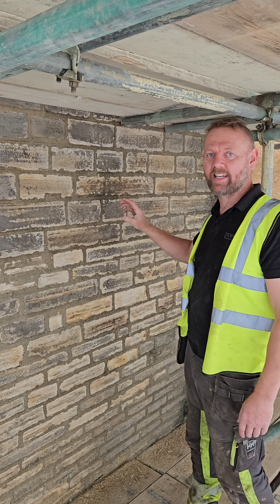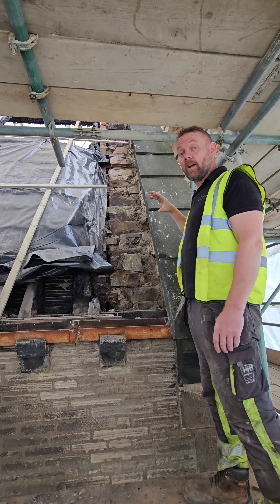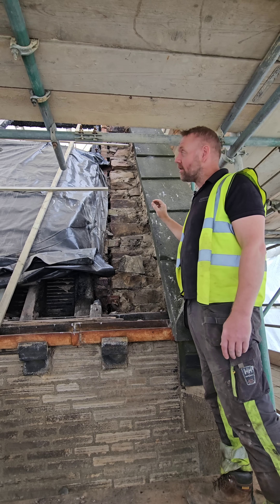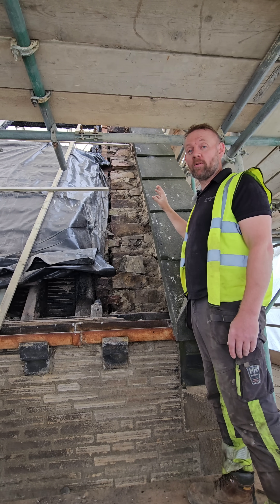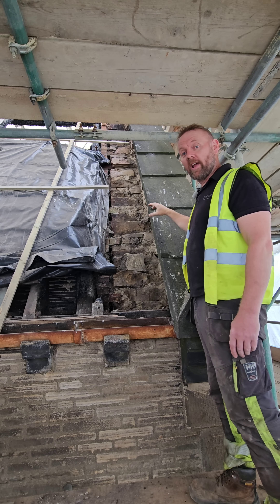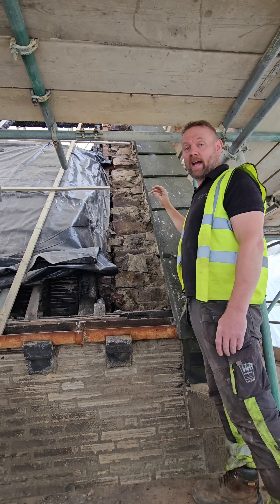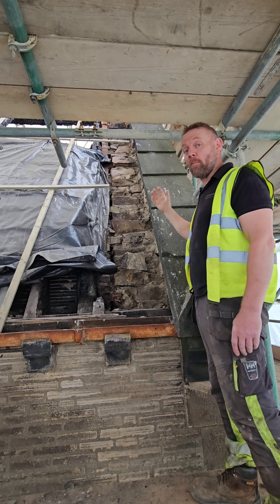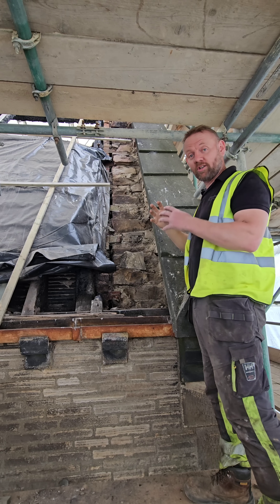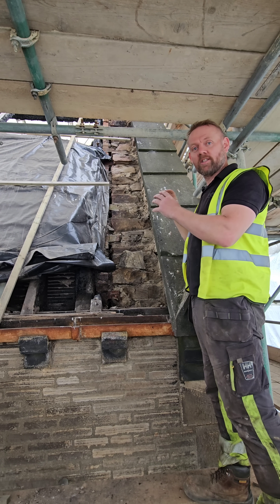This is the mobilization of salts in masonry in action. This wallhead has been exposed to the elements for about two years. We now have a tent roof over the chapel that burnt down, and the water has been migrating down through this wallhead. Because the salts have been diluted with water they've not mobilized, but now that the roof has been put on and the walls are starting to dry out, that moisture and those salts are being brought to the surface of the stone.